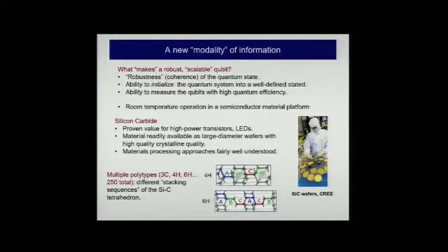There's an additional feature about these silicon carbide materials. They exist in a large variety of different, what we call, polytypes. That is, stable, single crystal structures in which there are different stacking sequences of the silicon carbon tetrahedron. Some of the most commonly used is called 3C for cubic, 4H, hexagonal, and I'm going to be dwelling on 4H, 6H. But it's amazing to think that there are more than 250 stable polytypes, and that actually people can grow these with some degree of reliability, and that you can control the sequence of the orientation of these silicon carbon tetrahedra with that degree of precision.